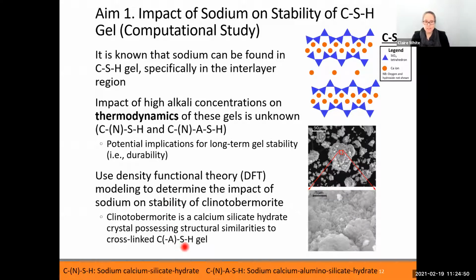especially when aluminium's incorporated into the structure, because clinotobermorite tends to have some cross-linking between the interlayer regions. And we also know when aluminium's brought into CSH gel, you also get that cross-linking happening within the structure. It's known from NMR results.